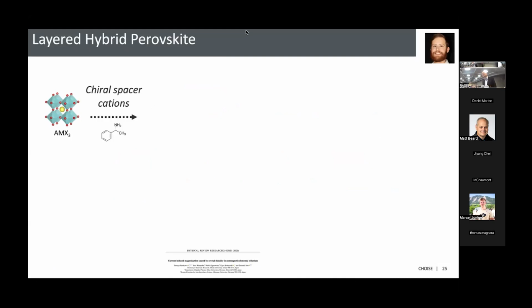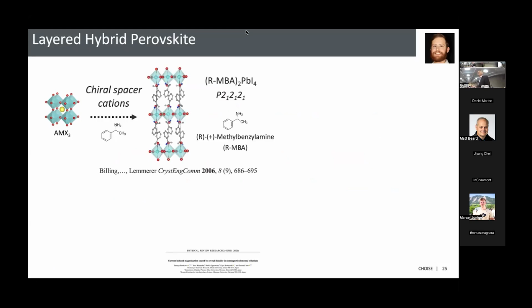So this is kind of the perovskite system, Matt Hautzinger over here. You take your three-dimensional perovskite system, you add this chiral amine, and you end up with this layered system. So you have layers of metal halide octahedra interspersed with these chiral molecules. And it has this space group P2₁2₁2₁. So this is sort of the prototypical chiral perovskite that we've been studying.